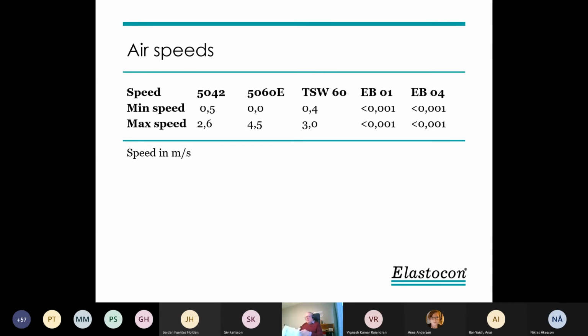And we come to air speeds. We measured the air speed at a lot of different points in the chambers, and we found that there was quite a variation depending on where we measured, from almost 0 to quite high air speeds. The speeds are given in meters per second, and that explains the result we got when we tested, say, the aging of rubber samples at different positions, that we got quite different results.